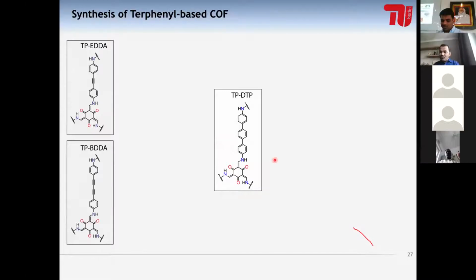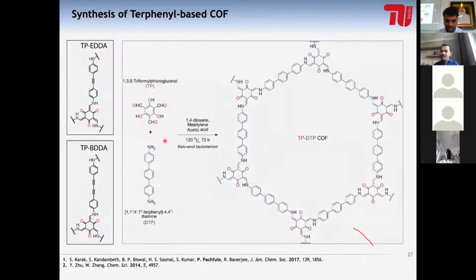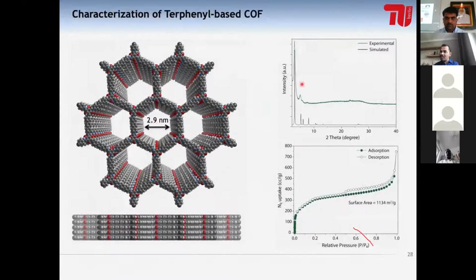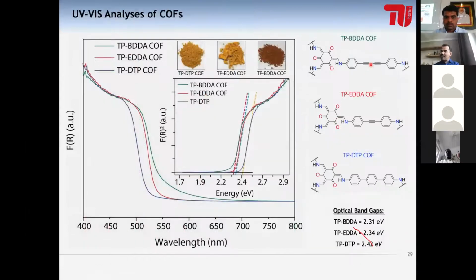And to do that, we have followed the exact same conditions as I showed earlier for these 2 COFs, and we got the material which was crystalline, which was even more porous as compared to the other 2 counterparts. And so now our target was that we had 3 COFs where there is a diacetylene moiety, there is an acetylene moiety, and there are just phenyl moieties in their backbone.